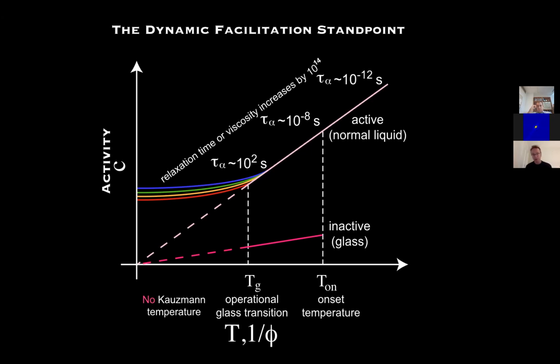There's the normal liquid, the active liquid, which gets slower and slower as we drop the temperature. And then there's this inactive phase, the glass that I mentioned. These would be the blue particles, and the active would be the brightly colored particles in the movie. And so it's a different story. It's a fundamentally different story.